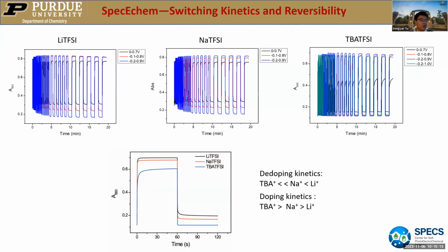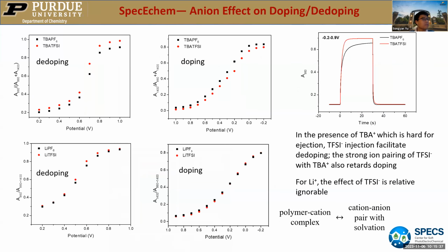And I also want to mention that this polymer is prone to dope. So in most cases, the doping kinetics is faster than the de-doping kinetics. So further, if we want to improve the device switching performance, in most cases we need to consider how to increase the switching speed of the de-doping process, not the doping. So here, we understand the cation plays an important role, but the anion also plays a role in the doping and de-doping process.